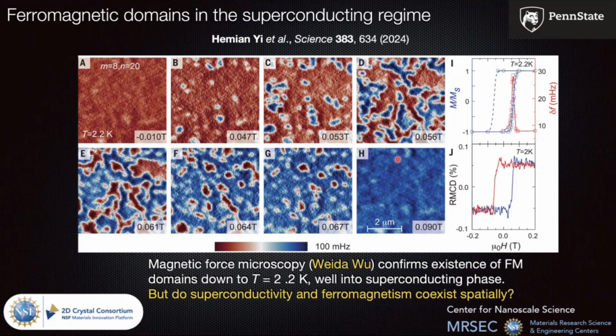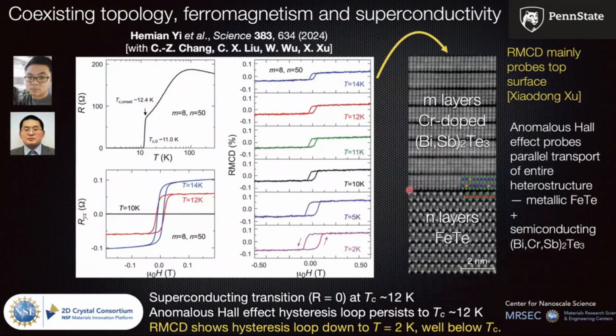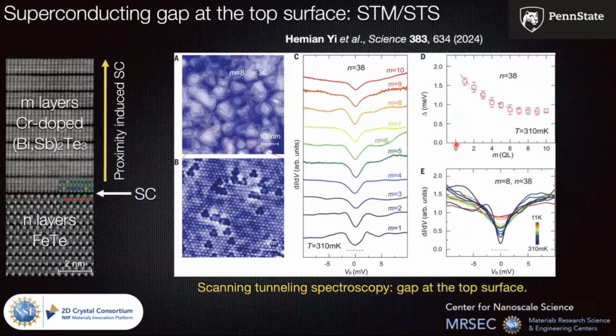But this doesn't answer a simple question. Do the superconductivity and ferromagnetism actually coexist spatially? Because you can imagine that what's happening simply is that you have superconductivity here, and then somewhere up here you have ferromagnetism, and they have nothing to do with each other, which is interesting, but not particularly interesting. So he fortunately managed to get a Unisoku scanning tunneling microscope installed in the meantime, and carried out scanning tunneling spectroscopy, and actually shows that you do get a gap at the surface. Now, presumably this gap is due to superconductivity, and one can make arguments that you can get gaps developing in the STM for all sorts of reasons. But I think he's made a strong case that this is actually a superconducting gap.